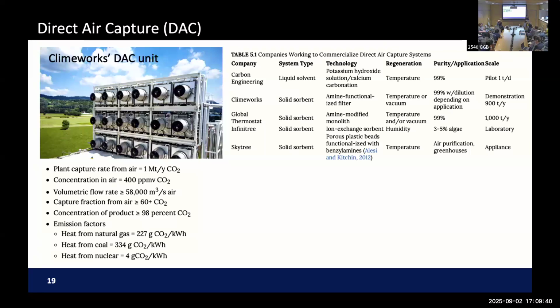So people start thinking about, okay, now we need to think about, again, similar to electrification of anything. We need to think about non-thermal energy transfer to do what we want to do. So when you have a material, at the end of the day, chemical engineers like me and mechanical engineers too, we love steady state process, isothermal reactors, right? So that you will have capture reactor and regeneration reactor operates at a very different temperature. This one will be ambient temperature if it is direct air capture. The regeneration reactor will be operating at 120, 140 degrees C. Means that this entire reactor wall, inside, sorbent material, everything has to be 120, 140 degrees C. But that's maximum energy penalty in a sense, right? Because you don't want to heat up all these things.